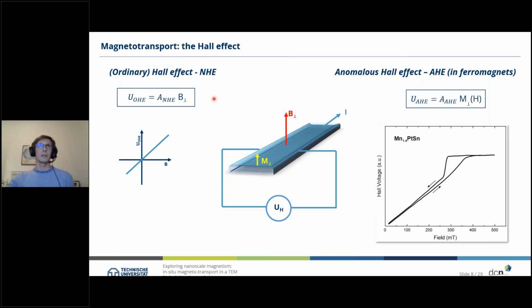And then we have, on the one hand side, the so-called ordinary Hall effect, which is mainly proportional to the applied field, so a linear proportion. And then we have, which is more important for us in the experiments I will show today, the so-called anomalous Hall effect, which mainly pops up in ferromagnets and which is proportional to the magnetization of your sample. And one example is shown here on the bottom.